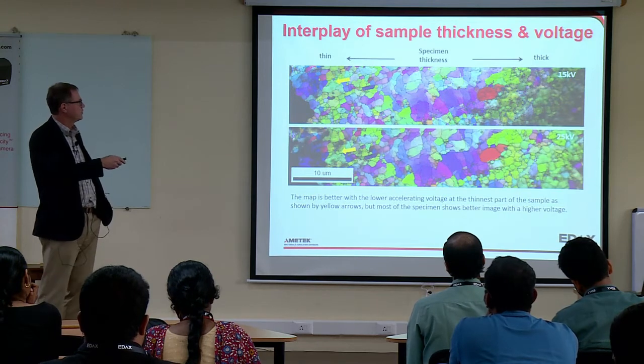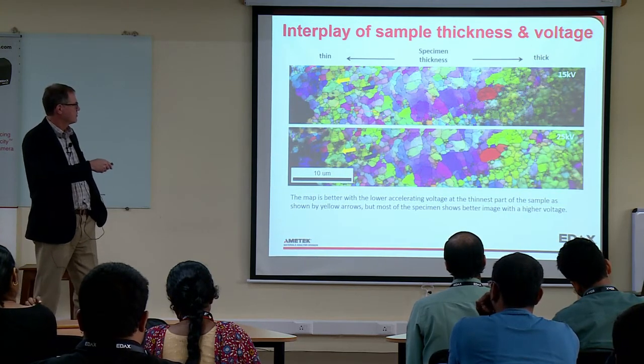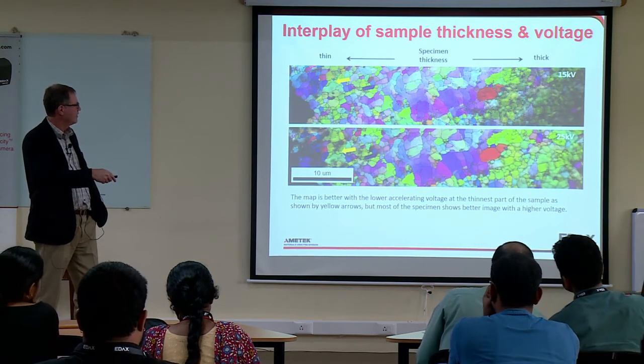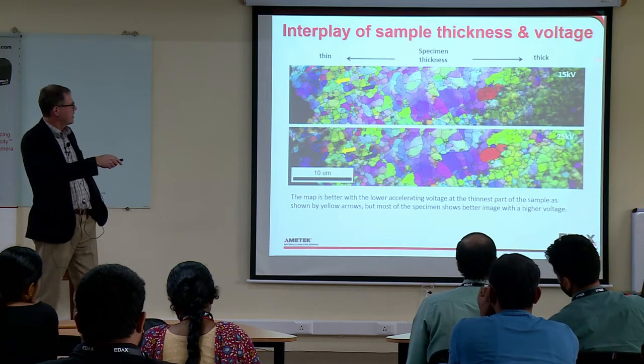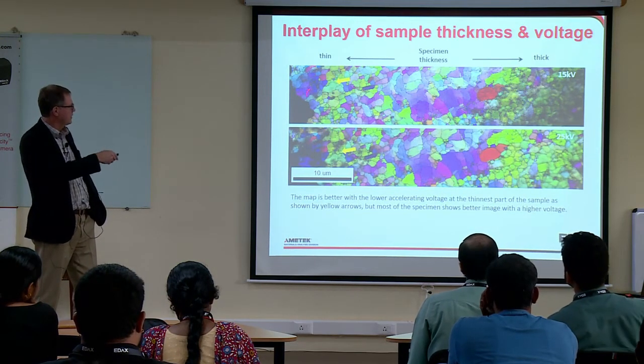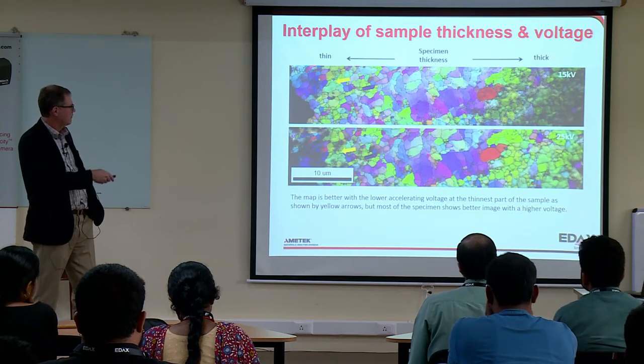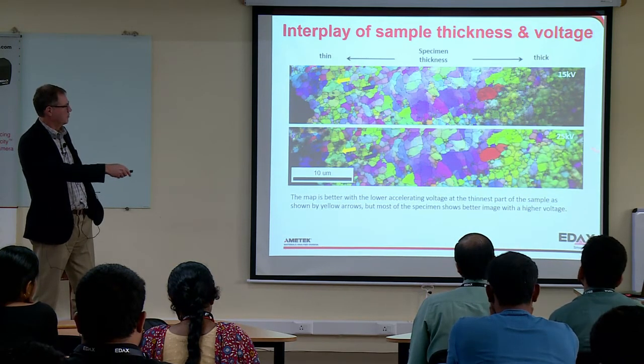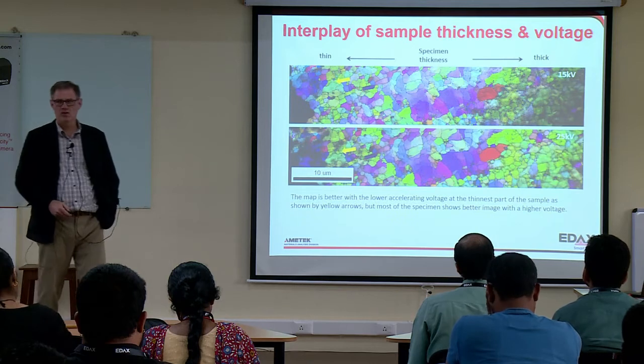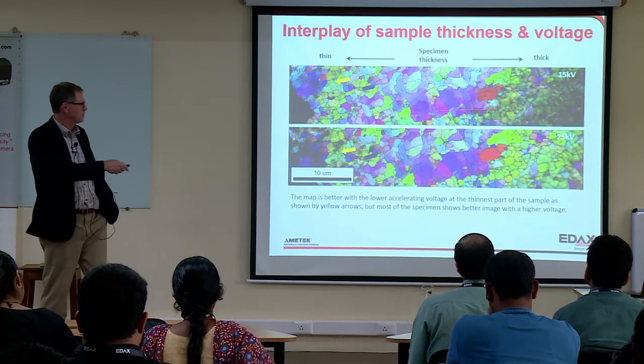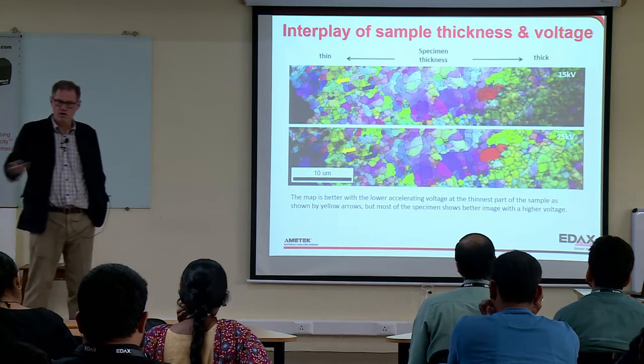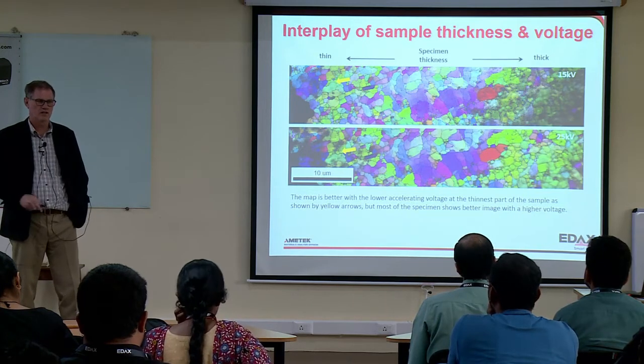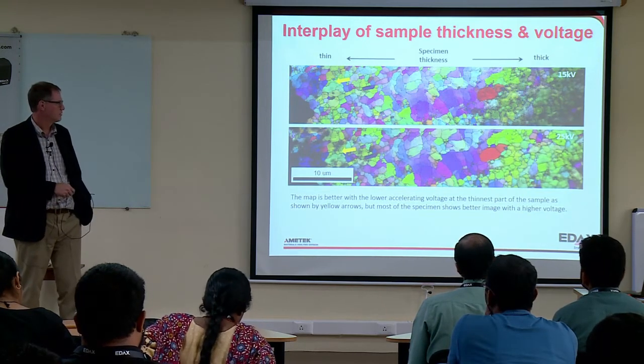Here's an interplay between sample thickness and voltage. So this is 15 kV and 25 kV. In the very thin sample at 15 kV, we image this really nicely. If we go to higher voltage, we don't image this very well, but we image this very well. So if you're having problems with the uniformity of the thickness, you could run it at two different voltages and merge the data together to get one good comprehensive picture.